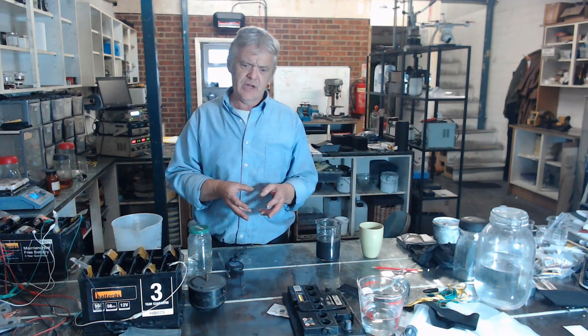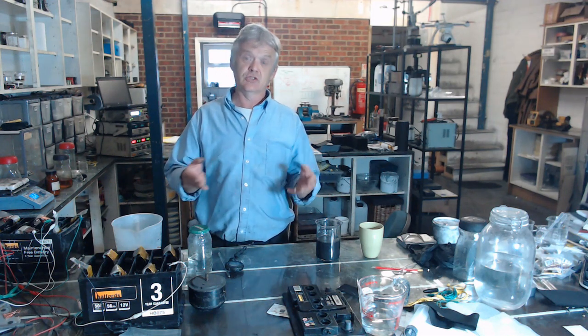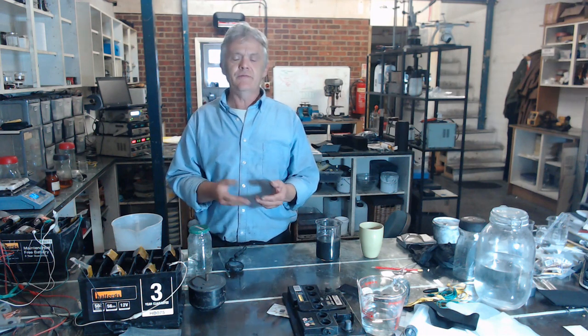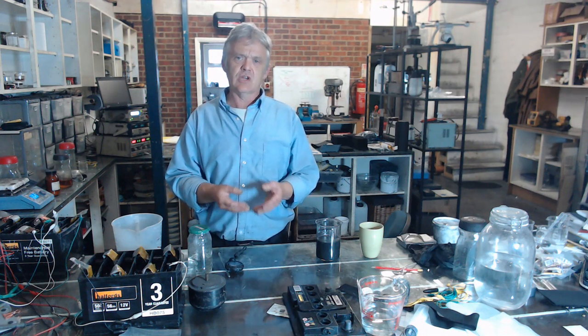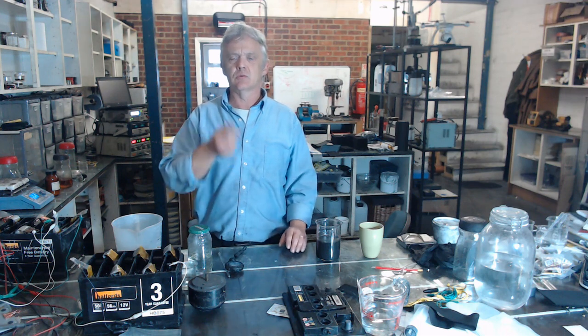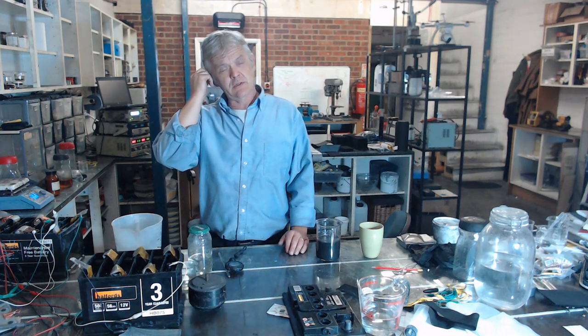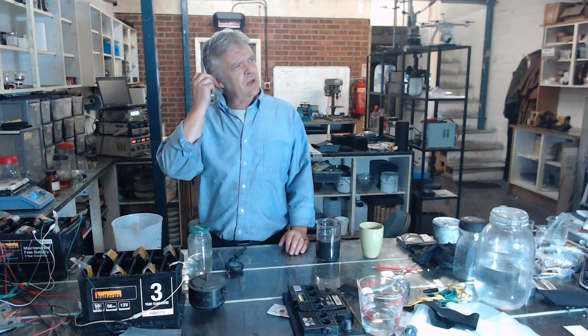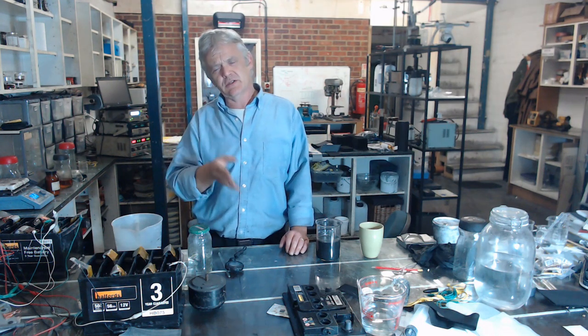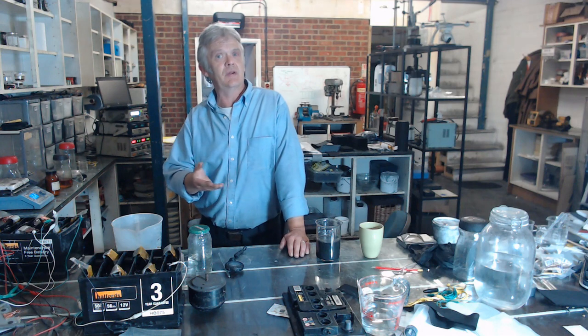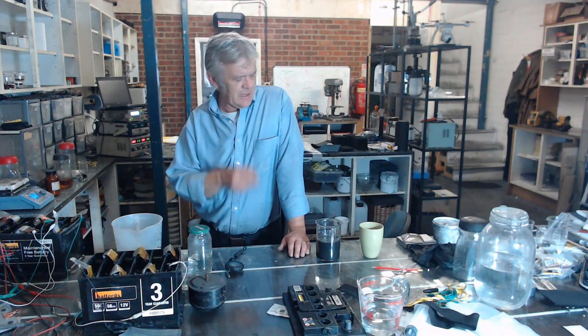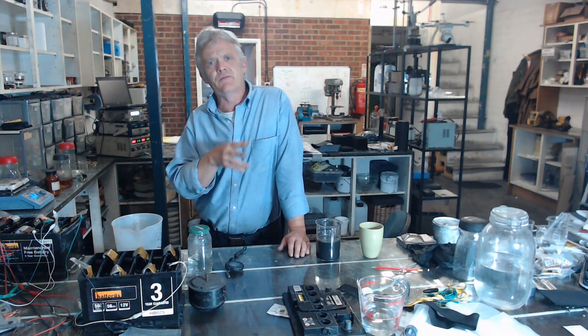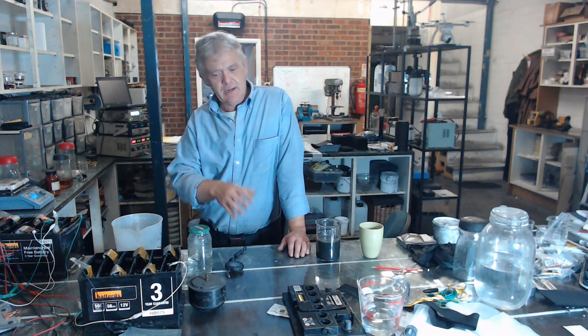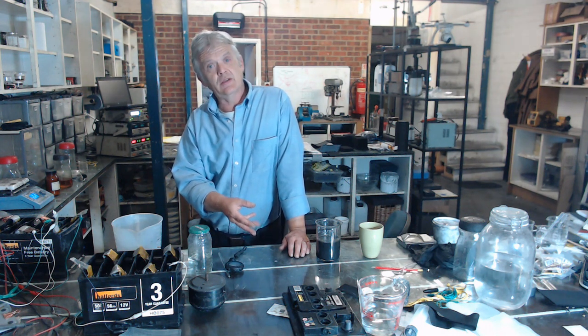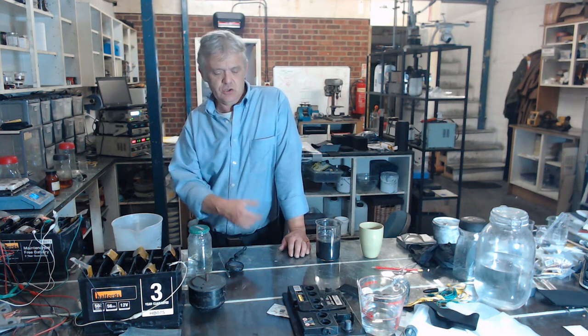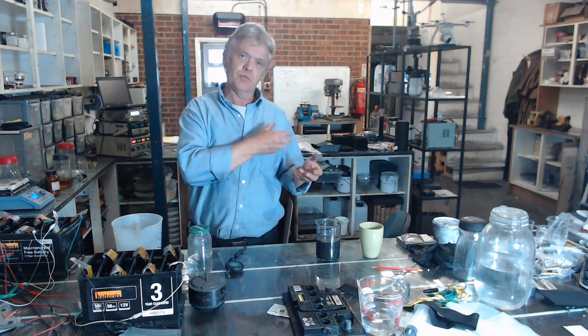So they crush it down to the liberation size, and then they use something called flotation. Obviously graphite is naturally hydrophobic, so if you put it in water of the right size, it will just want to float. You add something else to the water, it tends to be kerosene. So kerosene's added. They sometimes do a different pH, alkali pH, so they add sodium hydroxide to help stabilize the foam. And there was something else that they add as well, I can't quite remember, that helps for foam formation. But basically, you drop it in the water with these few additives, and it works better if they're starved. So not many additives. You drop them in, they float on the top, and you scoop them off.